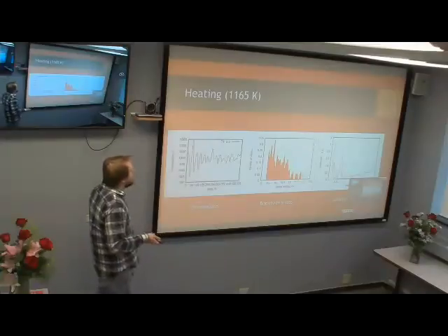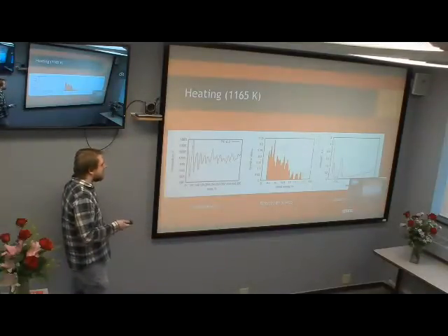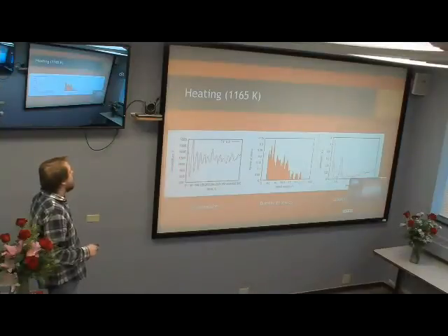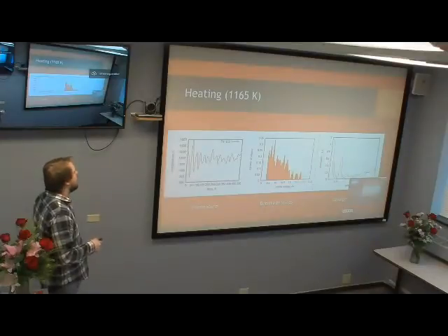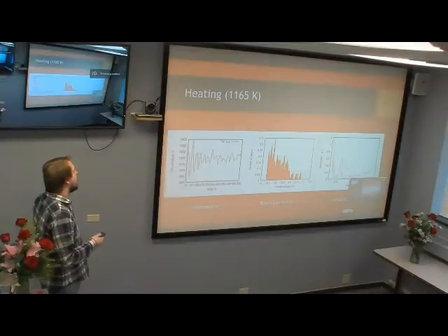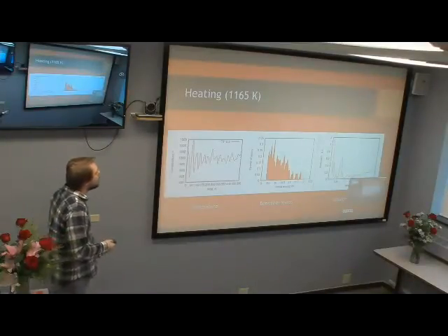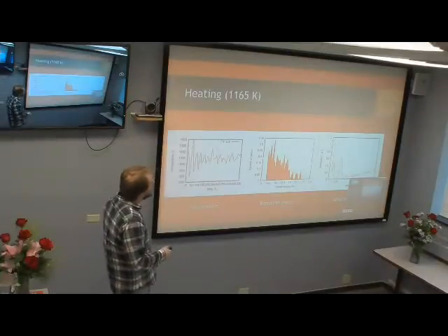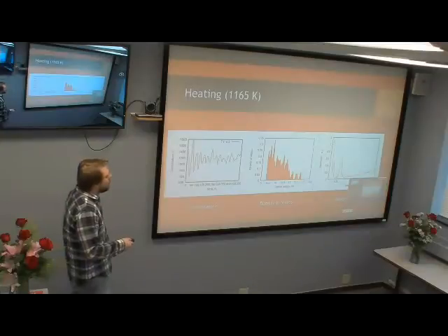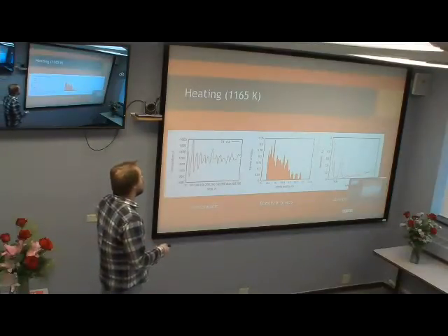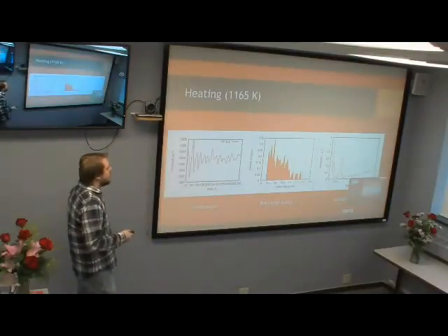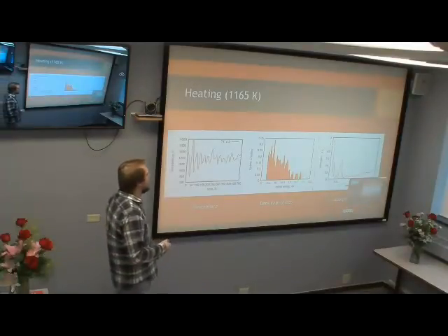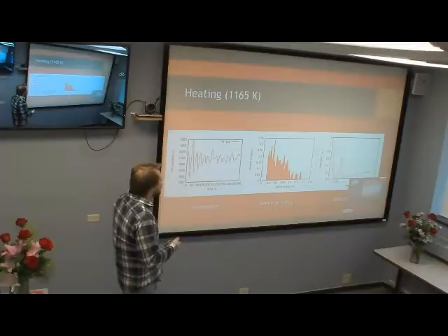After that, I heated just the PN junction and ran molecular dynamics. This plot shows the temperature as a function of time. There are some oscillations, but they all oscillate around an average of 1165 Kelvin, indicating thermal equilibrium. Over here is the density of states — what's odd is that there are unoccupied states in the valence band, which makes it look somewhat like the P-doped model without any heating. I'm not entirely sure how to explain that, but it's what I found.